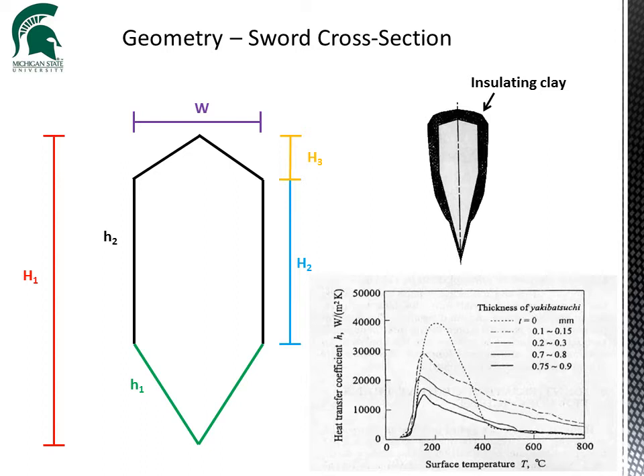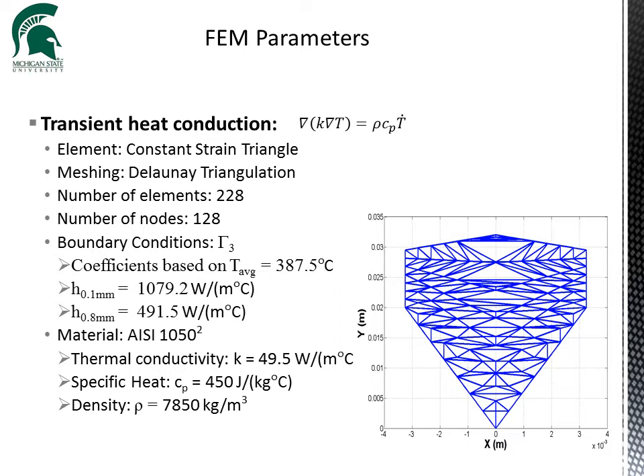The convection coefficients, little h1 and little h2, are determined based on clay thickness around the outside, as well as the surface temperature. The FEM study involves using 228 constant strain triangles with 128 nodes to model the cross-section. The convection coefficients for the gamma-3 boundary condition are based on the desired clay thickness and the average temperature of the starting and final surface temperatures. Steel is also used for the cross-section.